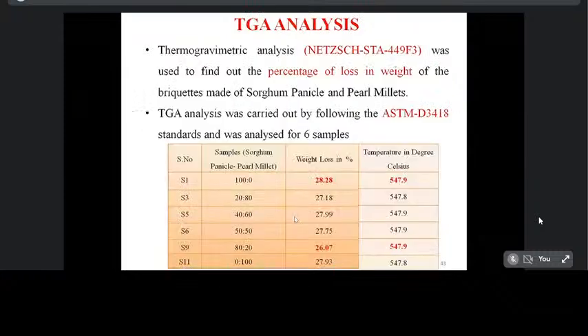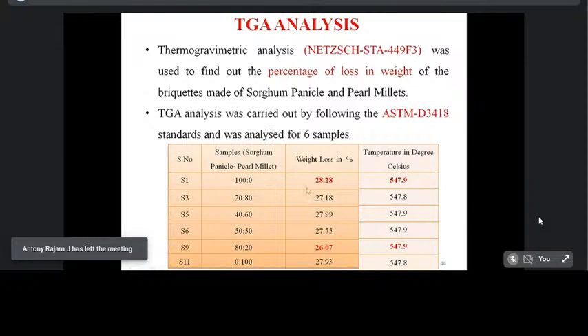Okay, so the TGA analysis. Thermogravimetric analysis was also done with the NETZSCH STA 449 F3 model, to find out the percentage of weight loss or the residual mass of the briquettes made from sorghum panicle and pearl millet. This instrument also works with the principles of ASTM D3418. Here, the 11 samples were produced from solid biomass waste, and we have taken only 6 samples for the TGA and DSC analysis, based on the carbon percentage.